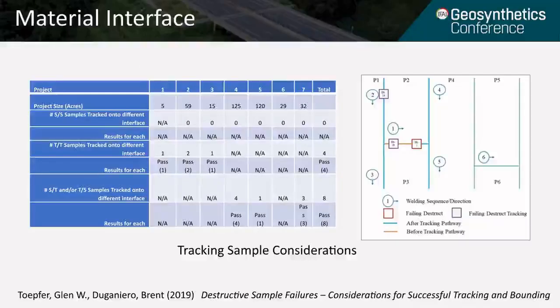In that same study, we also looked at when destructive samples were taken on a textured interface and they were tracked to a smooth interface or another textured interface. In all the cases we looked at, when they were tracked to a smooth interface, they immediately passed. And so there needs to be some guidance on how to make sure the other textured seams are not being missed and they're being accounted for somehow.